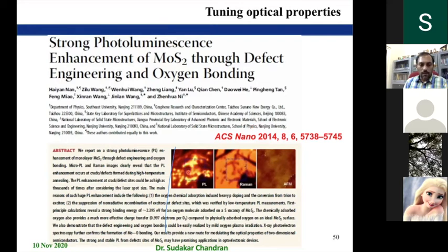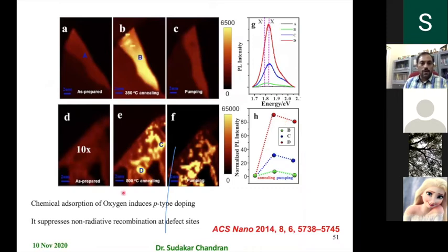In this particular work, they had a lot of cracks and defect sites, and from those places they see the emission being very high. They suggested that the non-radiative recombination of excitons at the defect sites is minimal. Therefore, it enhances the PL emission properties, and also the chemical absorption of oxygen induces p-type doping, and therefore this kind of material is interesting for photoluminescent applications.